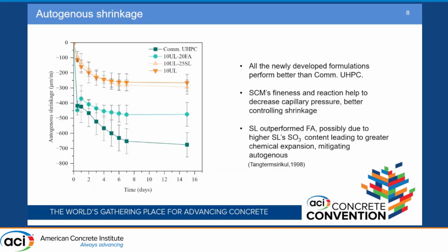So these are the first results of our ongoing research that I'm showing you. This is related to autogenous shrinkage, which you might know is a real issue for UHPC because it can cause internal stresses and crack our concrete, affecting the durability. In this case, our formulations actually suffer less autogenous shrinkage than the commercial UHPC. This was mainly due to the different SCMs that we used, which created for all these formulations a microstructure that shows larger pores, and that helped to decrease the capillary pressure that formed during hydration.